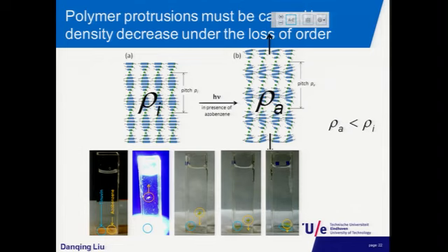And then by repeating this experiment with many different solutions with different densities, you can determine the change in density during this photoisomerization reaction, which is about 10%, and this 10% really nicely corresponds to the height differences that we are creating in our films. So if you have 10 micrometer films, we create protrusions of about 1 micrometer.